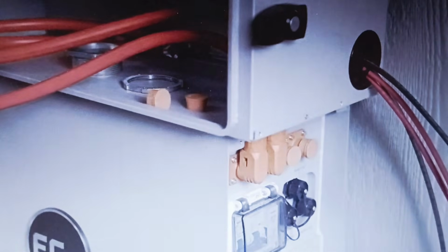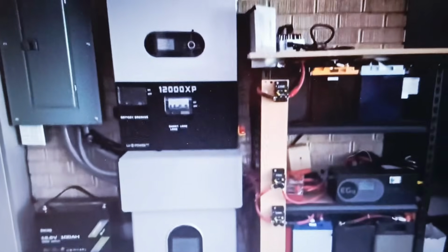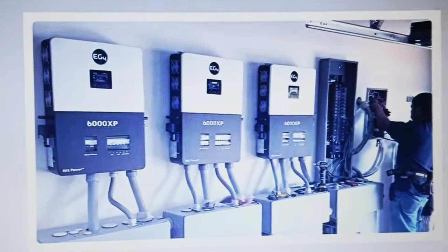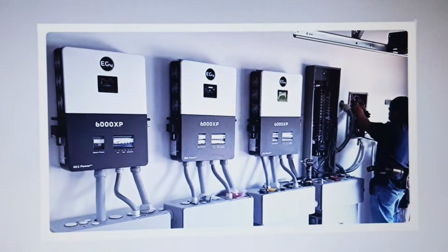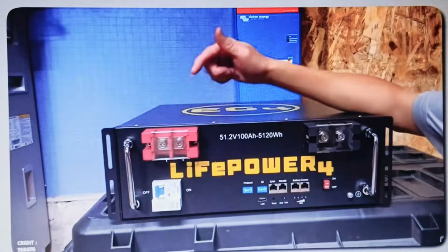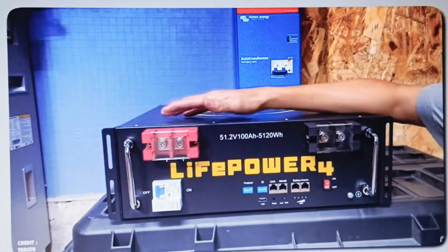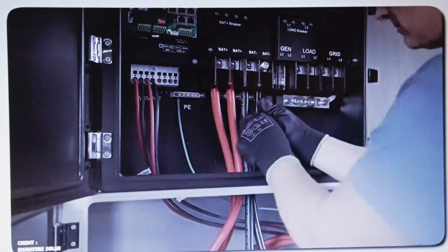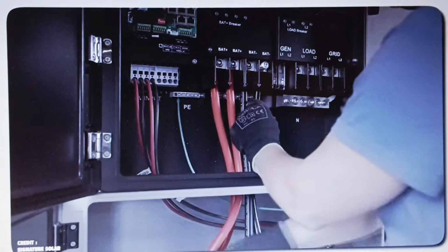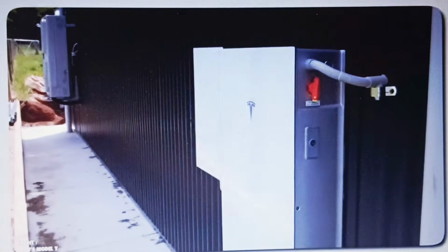Older lithium chemistries use cathode structures that contain cobalt, a conflict mineral with a genuinely troubling supply chain, and those structures become thermally unstable under stress. Overcharge them, overheat them, physically damage them, and they can release oxygen internally. Once that happens, you have a self-sustaining fire that water cannot put out.